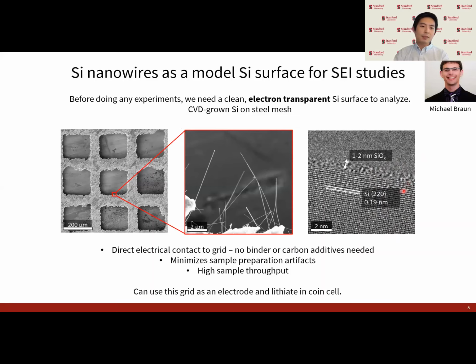And this results in a silicon system that can then be lithiated in a real coin cell and prepared with minimal sample processing and high throughput. And because of this, we don't need to use any additional binders or conductive additives that are commonly used in real battery composite electrodes, which only serve to further complicate the system.